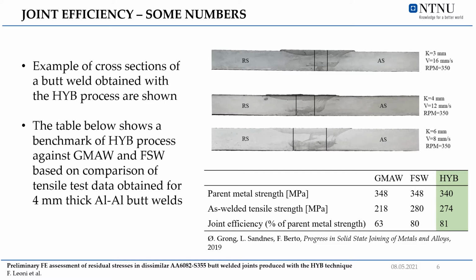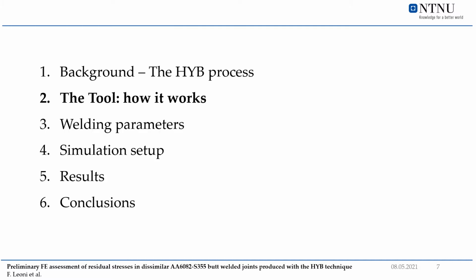To give you some quantitative information, the table below shows a benchmark of the HYB process against gas metal arc and friction stir welding, based on comparison of tensile test data obtained for 4 mm thick aluminum butt welds. Let's now see how the tool works.